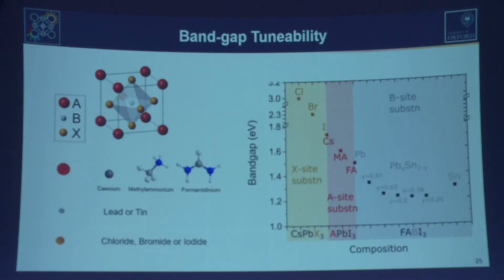I mentioned that we can tune the composition. We can basically mix cesium, methylammonium, and formamidinium. We can mix the halides from iodide, bromide to chloride. And in doing that, we change the crystal lattice size, which changes the band gap.